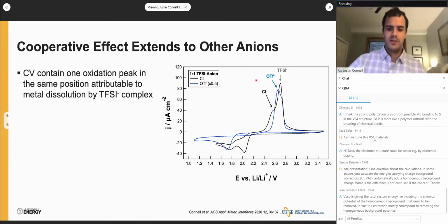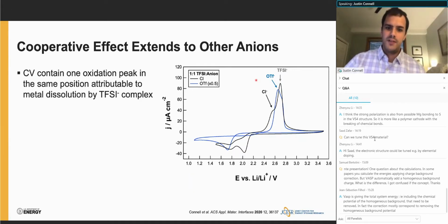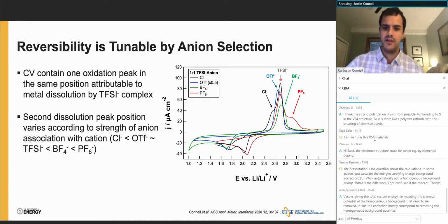So we return back to the predictions of DFT and we start to compare anions of differing association strength. We see, what I've already shown until now, the TFSI chloride and TFSI triflate case, we see the additional oxidation event to lower overpotential relative to the TFSI only. If we move to more weakly associating anions, though, very interestingly, we see the location of this additional oxidation event shift to higher overpotential, in direct analogy to what's predicted by the DFT.